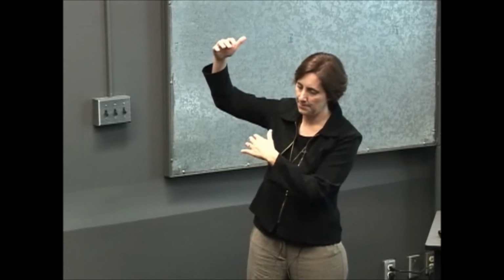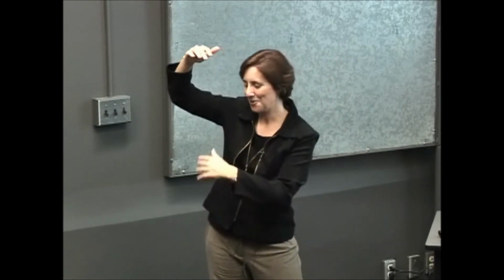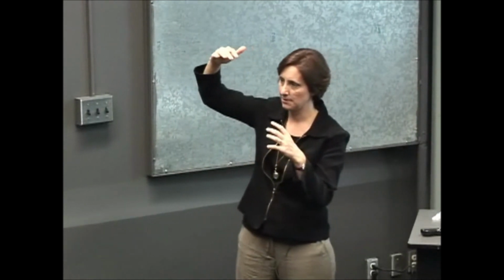Calculating, we work with some theorists at Los Alamos. Measuring, we just started some electrochemistry work in my lab. Yagna, who is one of the giant quantum dot ladies there, is trying to really pinpoint where the valence bands and conduction bands are. And what's odd, as a function of core size, typically everyone says it's the conduction band in the cadmium selenide materials that moves around when you go from bigger to smaller size, and that the heavy hole keeps things kind of stuck in the valence band. But some of our measurements so far are showing the exact opposite. We changed the size from big to small, and the conduction band is staying, and the valence band is moving.